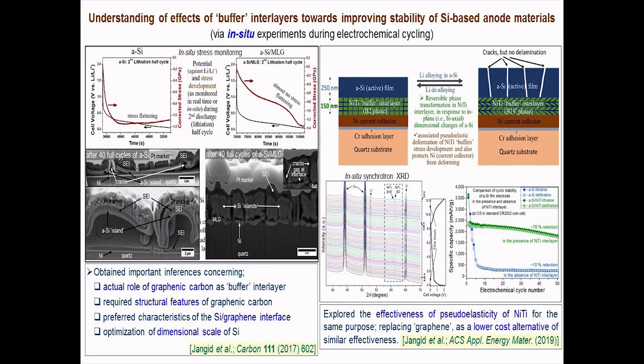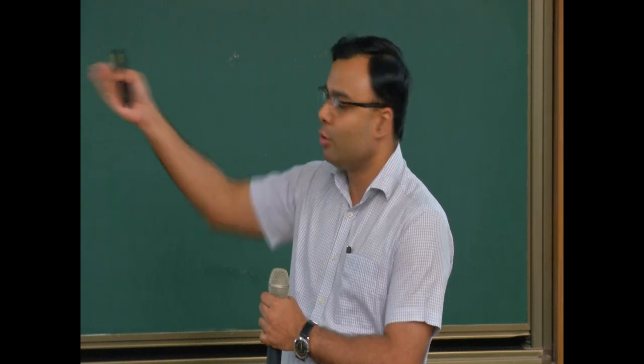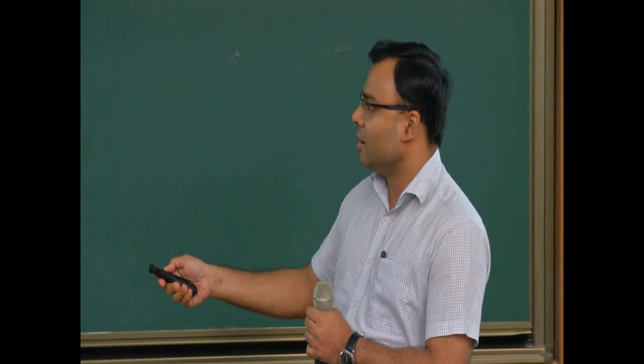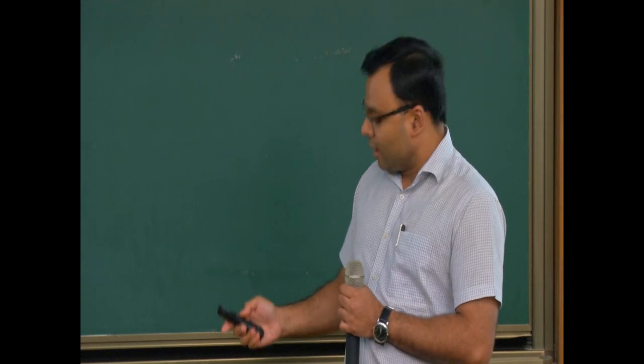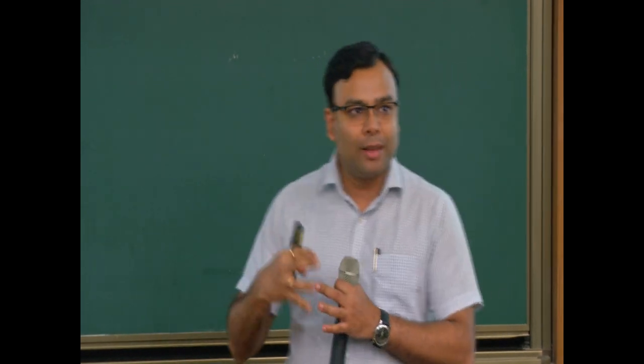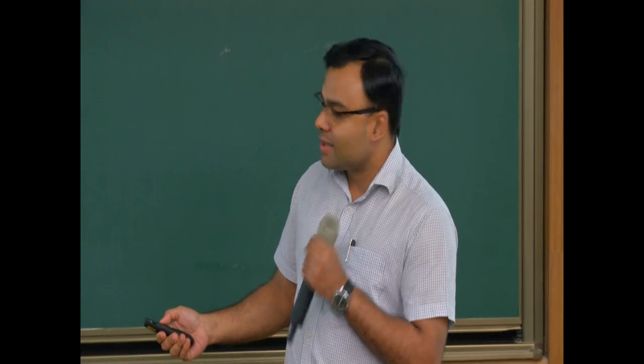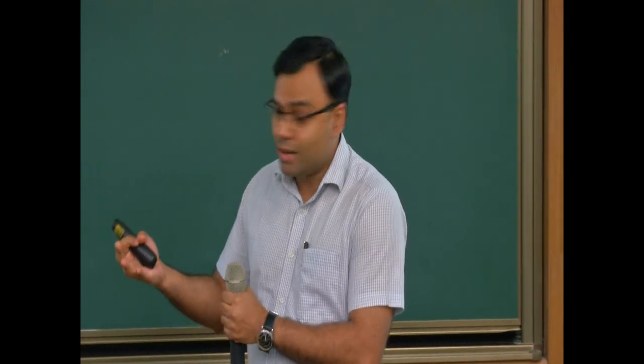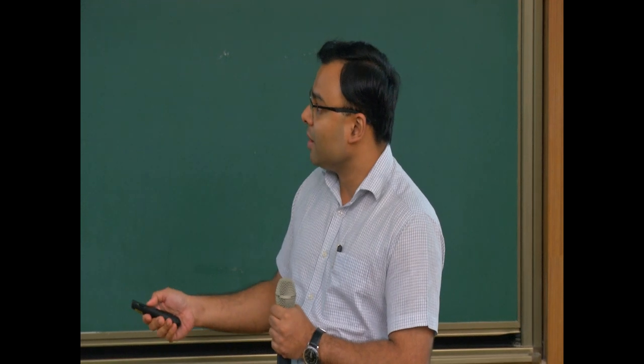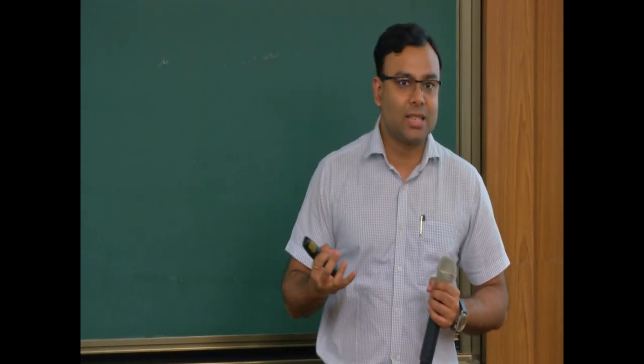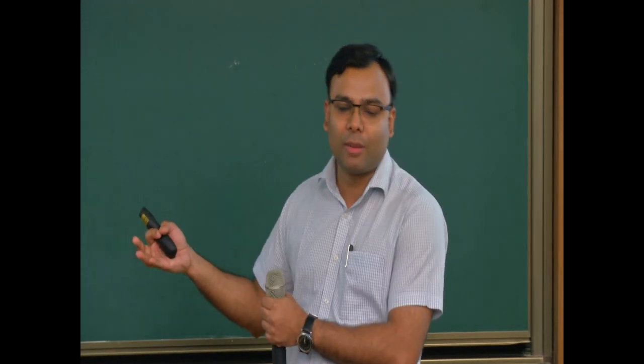Now, it is very flat when the oxygen network is quite robust, so that during further lithiation, delithiation, the energy of the site where the lithium is going into does not change appreciably. So the overall energy will remain the same irrespective of whether you put 0.5 lithium or 1 lithium, and so the voltage remains absolutely flat. However, if there is some deformation taking place in the oxygen lattice, then the site energy will change, even for a similar site like an octahedral site, and so the voltage will become much slopey. So it is again just the materials aspect, a solid state chemistry aspect, which is governing the electrochemical behavior in this case.